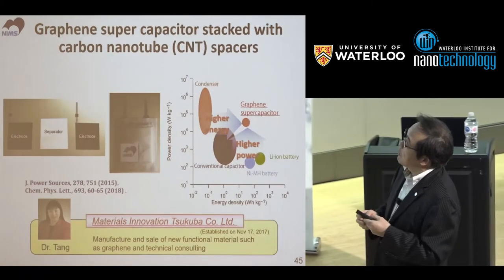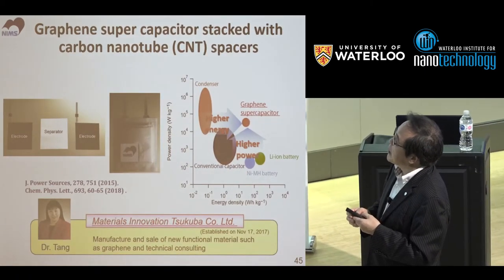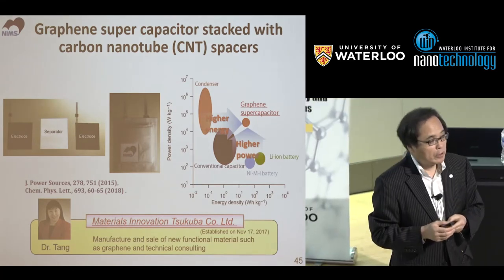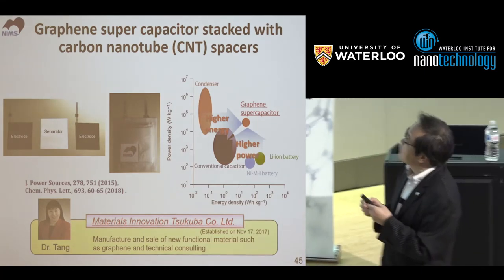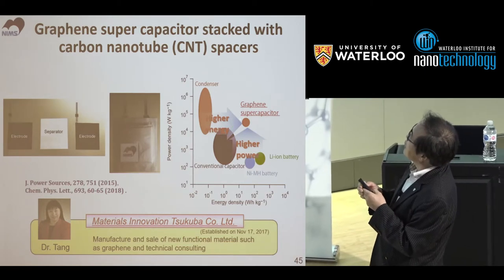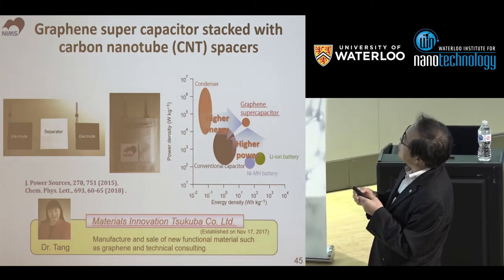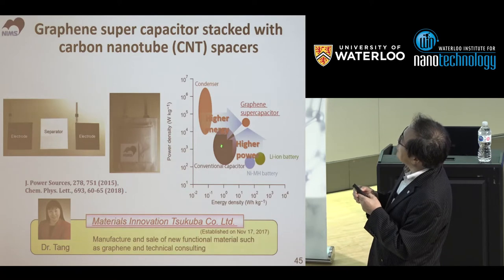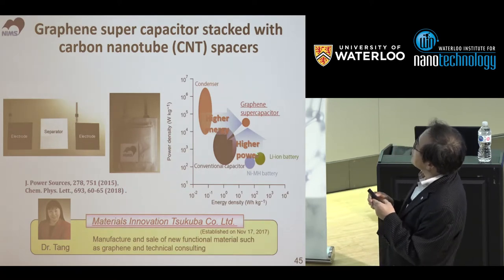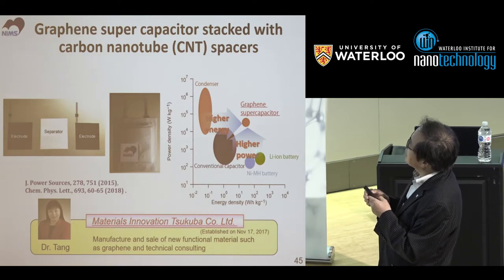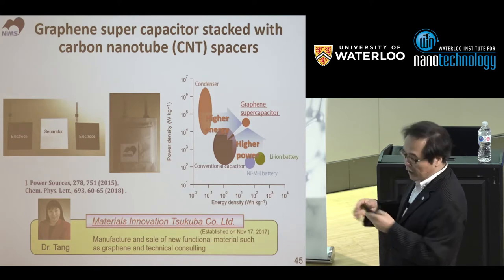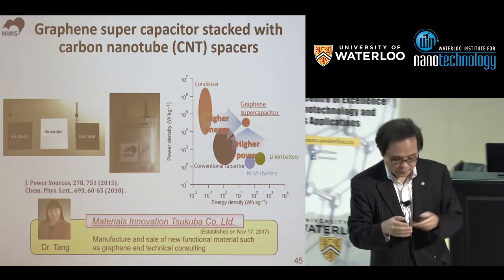And she fabricated a supercapacitor using the material. Interestingly, the graphene supercapacitor's power density and energy density are both higher than the conventional one. Compared to lithium ion batteries, the energy density is a bit smaller, by one order of magnitude, but of course the power density is very high. So that's why this has a very unique character.